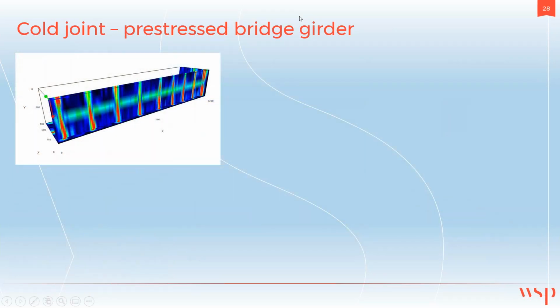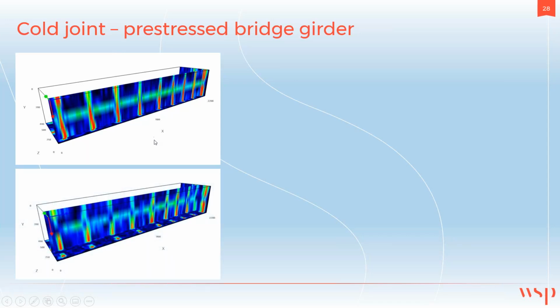For example, here we see the plan view, which is also called C-scan. This is the plan view at the depth of the top rebars, and we also see the longitudinal bar behind the vertical bars. I can move this C-scan farther away from the test surface, and then I can see the second level of rebars. But you can still see the first level of rebars, which would be these red dots here.